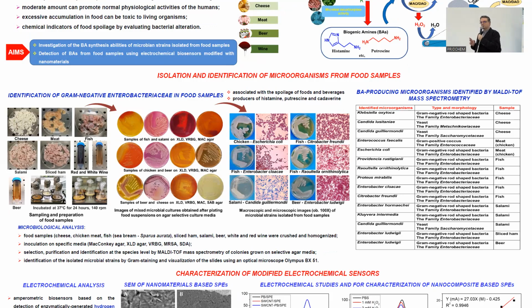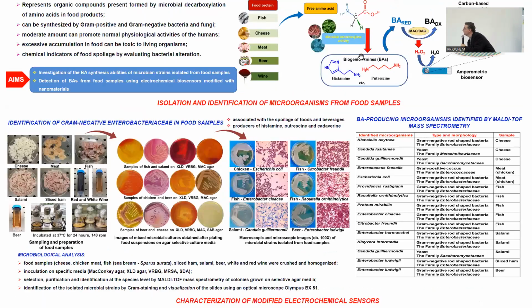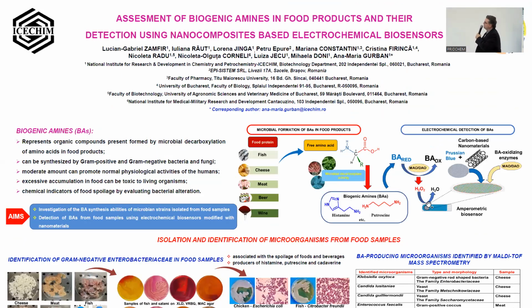After the identification of the microbial species, electrochemical studies were carried out using electrochemical biosensors. Screen printed carbon electrodes were modified with nanomaterials based on single wall carbon nanotubes and the redox mediator, Prussian blue. These were used for the electrochemical detection of hydrogen peroxide resulting from the enzymatic oxidation of the biogenic amines by mono or diamine oxidase.